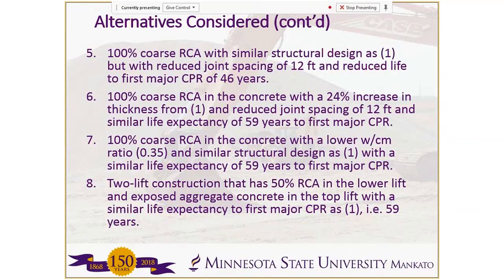Similarly, we had alternatives 5 through 7 with 100% coarse RCA. Again, we had some alternatives that were looking at an increase in thickness. For example, number 6, 24% increase in thickness. Alternative 7, let's lower the water cement ratio and try and get equivalent performance. So number 7 had a lower water cement ratio. We also took a look at the economic analysis of using the mix designs that were used in the MnROAD two-lift construction. We had the mix designs available, so we also looked at that in our economic analysis.